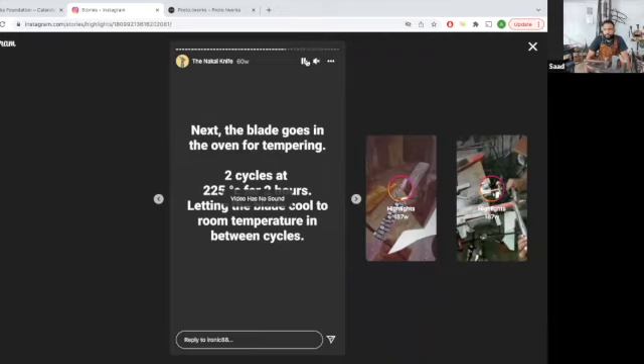So now after hardening the blade, again it's hard, but it's very brittle because you've suddenly made it quite hard. So you relax some of the stress by tempering it. Now this temper varies with what sort of knife you want. If you want a super flexible knife, you do a different tempering cycle. If you want a nice chopping knife, you do a different tempering cycle. You do this in the oven.